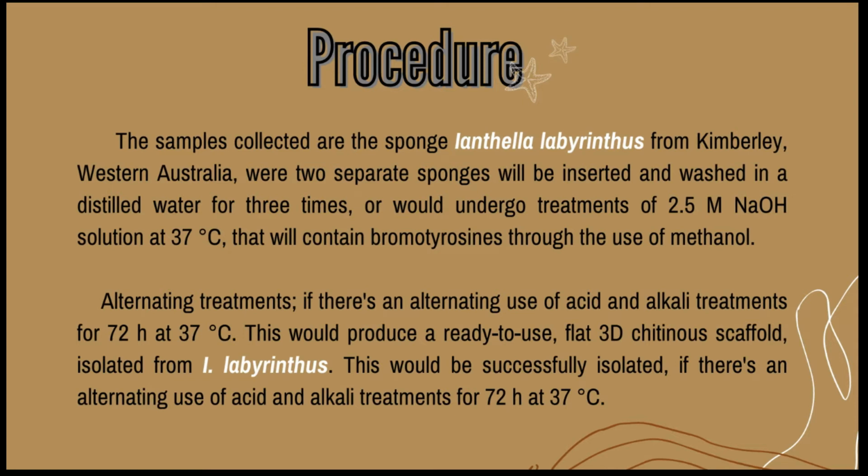After the 24 hours insertion of Ianthella labyrinthus in the distilled water at room temperature, its typical flat, mesh-like architecture should be visible. Meanwhile, after the 48 hours treatment with 2.5 M NaOH at 37 degrees Celsius, bromotyrosine containing extract and bromotyrosine containing flexible skeleton of Ianthella labyrinthus should also be seen.